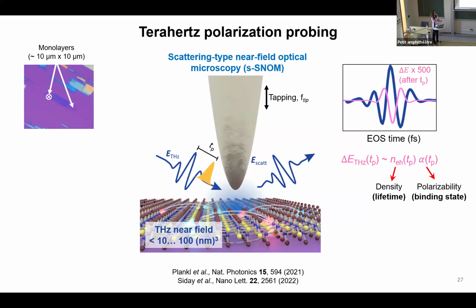So we record the reference terahertz pulse for our reference because we need relative amplitudes and so on. Also the scattered terahertz pulse when excitons are there. It means after pumping the system. And the way we technically perform it is that we have double demodulation at the frequency of the tip together with an optical chopper. So there are some technical details behind it.